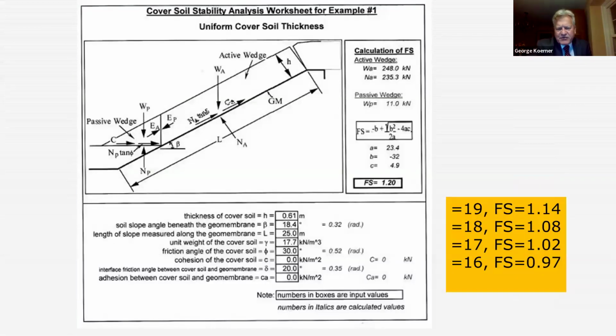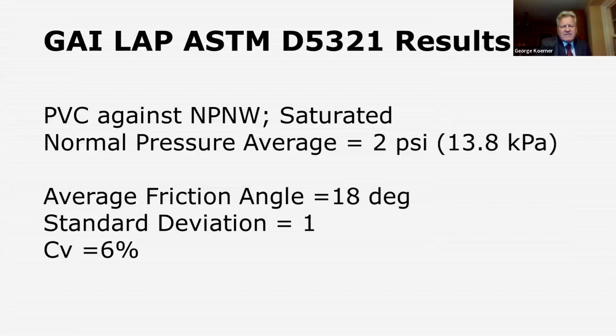And from a very elementary review of this computer program, you can see when the friction angle is 19, the factor of safety is 1.14. When it's dropped down to 16, it goes below unity. So this is the design for the PVC against needle punch non-woven in a saturated condition, run with ASTM D5321. Normal pressure of about 2 psi or about 14 kPa. The friction angle was 18 with a standard deviation of 1. I'm very proud of this sequence of data. 15 labs participated, and they did yeoman's work in this regard. And it really shows the power of running this, and certainly these results can be used in design.